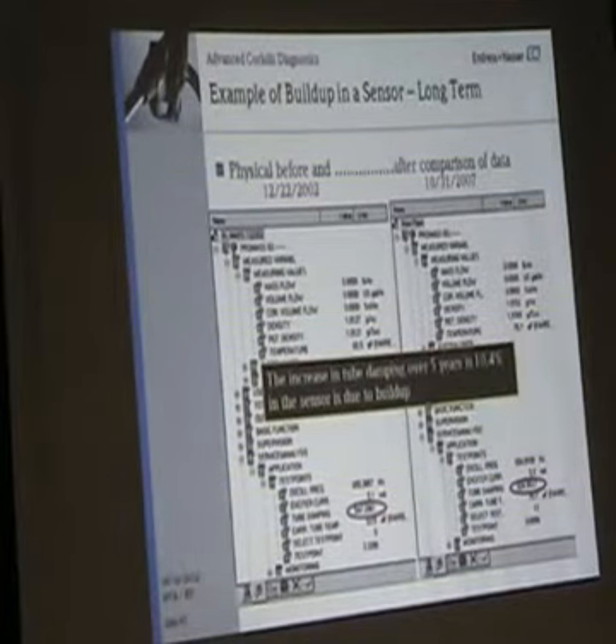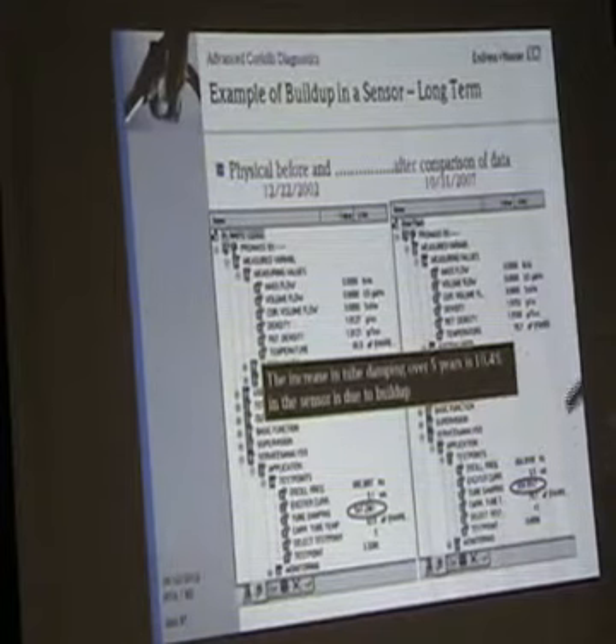And you can see there's the density, the mass flow, and these are the things that we're really interested in. Tube damping and excitation current. These are all the values that we can get from it. These are the values from the fingerprint. And in this case, you can see there was an increase of tube damping over 5 years of 11.4%. And that tells us that there's buildup in the sensor.